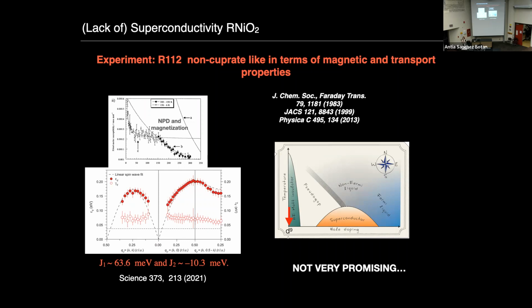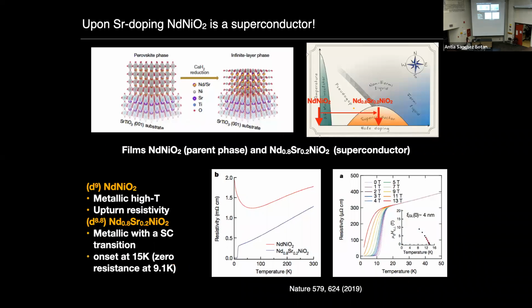Let me move on to something else. And by people, I probably mean ourselves too. But of course, we know that we were totally wrong because superconductivity in these materials is actually possible. So this here is just a snapshot of the original Nature paper from Harold Hwang's group, in which they looked at films of neodymium nickel oxide 2, that's the parent phase, and also of 20% hole-doped neodymium nickel oxide 2.